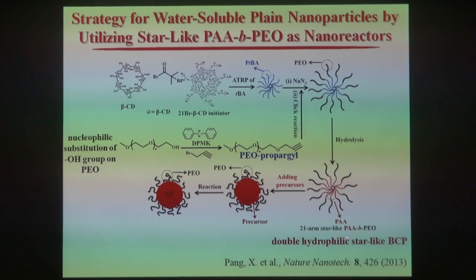To do that, first of all, we need to do the rational design to make a double hydrophilic star-like copolymer. This star-like copolymer is composed of inner hydrophilic polyacrylic acid, PAA, and outer hydrophilic polyethylene oxide, PEO. Then you add precursors. Again, the metal moieties of your precursor can selectively react with the carboxylic acid groups of PAA, forming nanoparticles. Now, this nanoparticle, because of capping by PEO, is water-soluble.